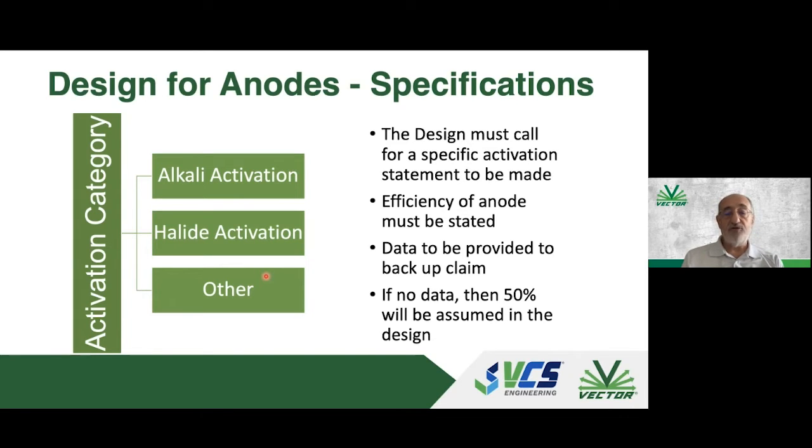It's saturated lithium hydroxide, which gives you a constant pH, and if you can maintain that lithium hydroxide content at saturation, you will get the same performance from the activator. So it's primarily the reduction in the surface of the zinc, and therefore the surface area, that diminishes the current. There are other things, but that's primarily the reason. Halide activators tend to have a lower, in fact, considerably lower aging factor. And if a manufacturer doesn't give you an efficiency, for example, then you have to assume 50% out, I think.